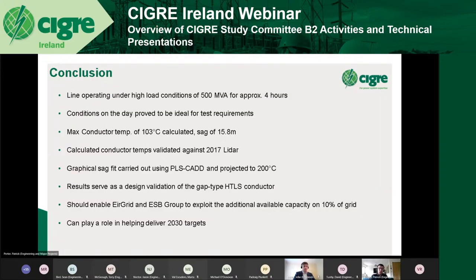Conclusions then. We successfully completed a high temperature test on an in-service major 220 kV circuit. We had a line operating under a period of high load for nearly 4 hours. As you've seen from the slides and the graphics, the conditions on the day really did prove to be ideal for a high temperature test. I don't think we've even had a day like that since. So we were lucky in many ways. We calculated a maximum conductor temperature of 103 degrees Celsius, so well in excess of 50 degrees over the ambient, which we set out to do.